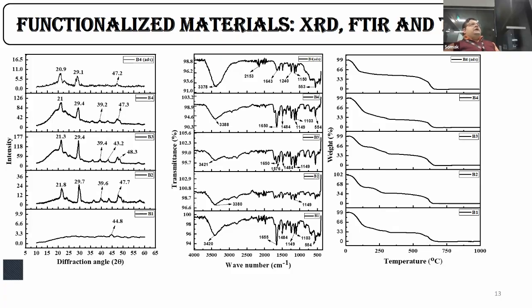In the TGA, that is thermogravimetric analysis we did, we can see that the major weight loss occurs at a temperature of around 600 degrees Celsius. The degeneration mainly starts at around 100 degrees Celsius, and it completely degenerates at a temperature starting from around 600 to 650 degrees for all the beads.